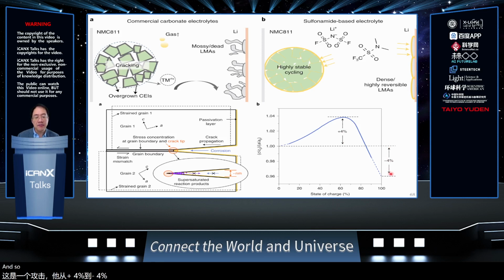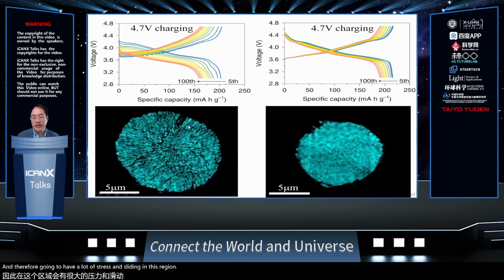And so traditionally, people found that there is a lot of cracking in the system because this grain boundary is not an invariant plane. In other words, you have two adjacent crystals, but their grain boundary length is not preserved. And therefore, you're going to have a lot of stress and sliding in this region. So with synchrotron imaging, we can see that if we charge to 4.7 volts, then after 100 cycles, there's a lot of cracks in the secondary particle.